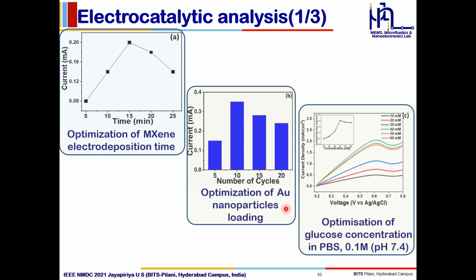It was found that an applied potential of 0.18 volts for 15 minutes of electrodeposition time gave a better current output. Next, the number of cycles required for electrodeposition of gold nanoparticles using cyclic voltammetry was also optimized. It was found that as the number of cycles for gold deposition increased, the gold loading also increased, whereas after a particular number of cycles, that is 10, even though the gold nanoparticle loading increased, it gave a lesser current output. This was because when the number of layers of gold kept on increasing, the size of the particles also increased. Hence, the number of cycles was decided to be 10 and has been used for the further experiments.